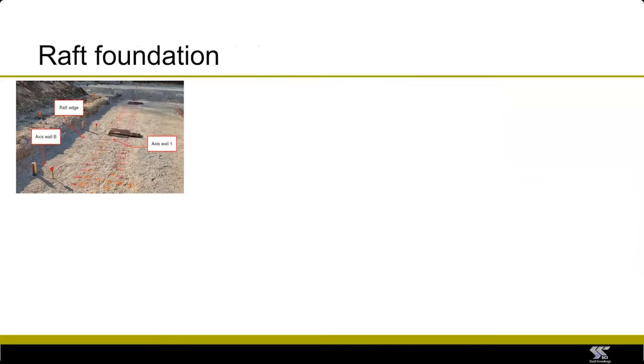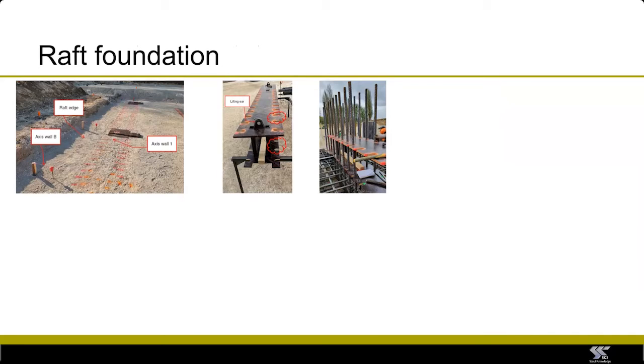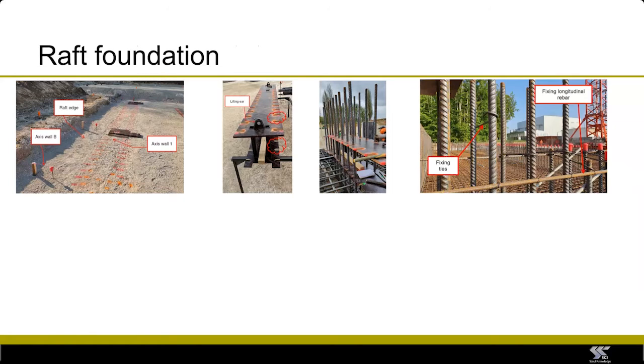The foundation for the building was a standard raft foundation. What was special about it was the need to position the starter bars very accurately, so we did not have any clashes between the starter bars and the steelwork of the modules. So the positions of the starter bars were initially marked accurately on the ground, and then a template was made that was used for ensuring that the positions and the spacings of the starter bars were accurate, also the verticality of the starter bars by having 2 layers within that template.